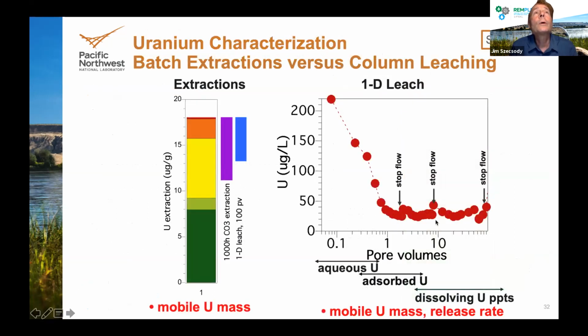So here's an example where I'm comparing a 1D leach experiment result to extractions. I'll start with the 1D leach. On the x-axis, this is basically time, but I'm plotting it in terms of pore volumes, and I did put it on a log scale. Vertical axis is uranium concentration. This is a contaminated sediment, and when you inject groundwater in one end and collect the sample at the other end, you see initially high uranium concentrations coming out, and it levels off to a low concentration for a very long period of time. And notice that this concentration didn't go to zero, so the sediment is still slowly releasing uranium.